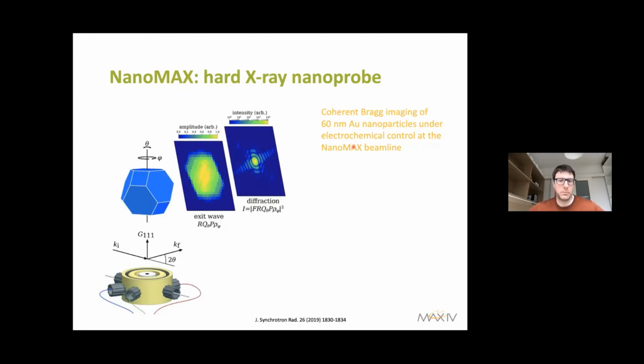And they proved that in principle it could be done, and this is due to the high coherent flux from the NanoMAX beamline. The problem in these experiments is that under the synchrotron beam, the nanoparticles are so small they tend to rotate. So you need to have extremely fast data acquisition, down to seconds or even sub-seconds, in order to do a complete stress map. And in principle, that will be possible with fourth generation storage rings.